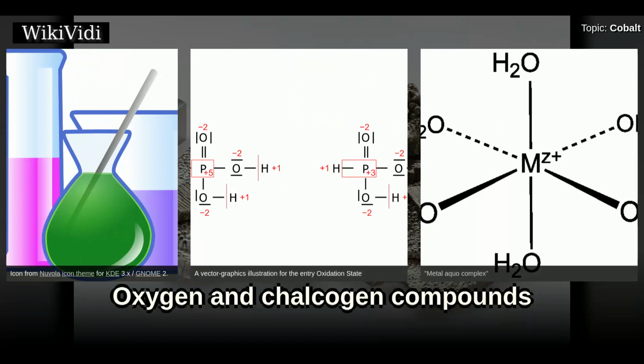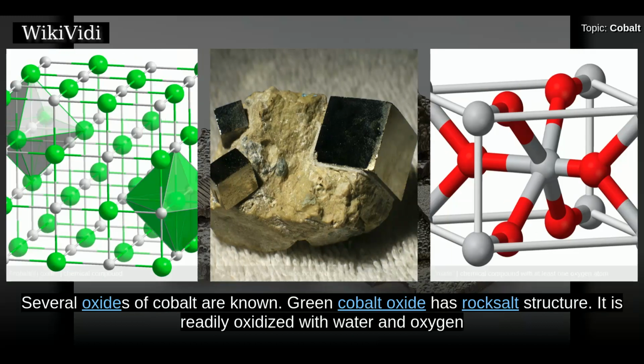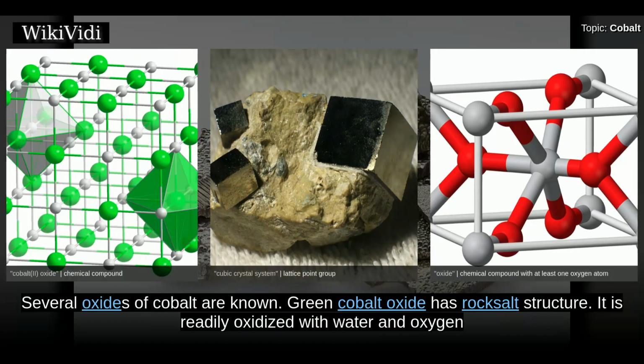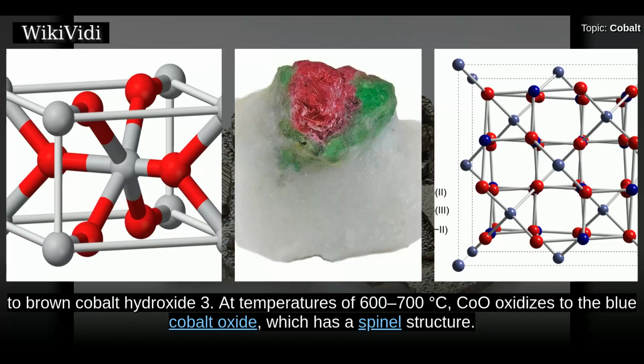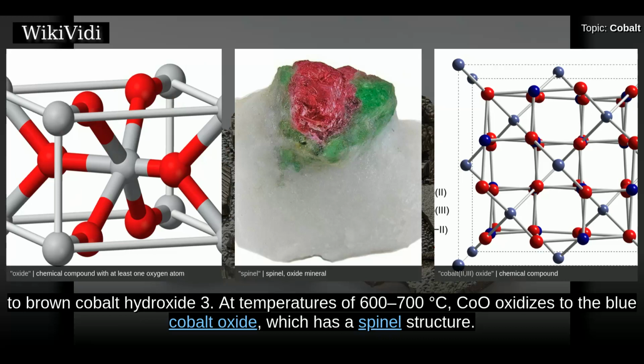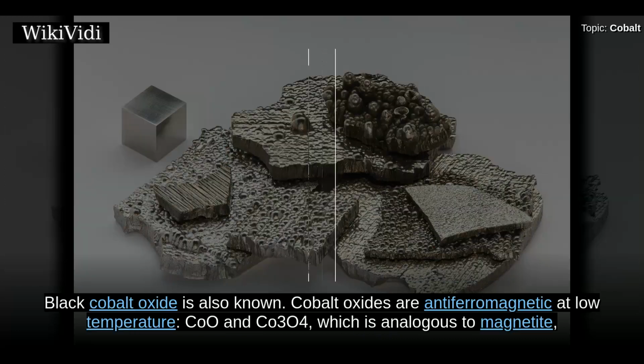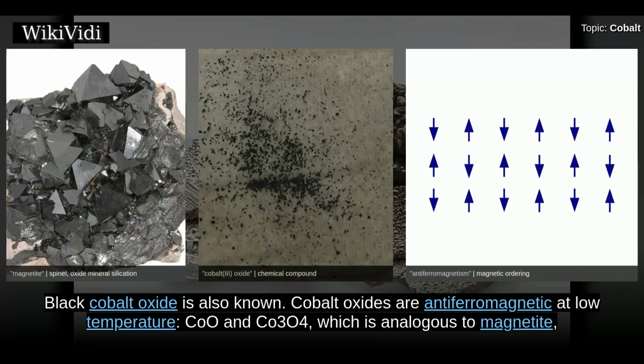Oxygen and chalcogen compounds. Several oxides of cobalt are known. Green cobalt(II) oxide, CoO, has rock salt structure. It is readily oxidized with water and oxygen to brown cobalt(III) hydroxide, Co(OH)3. At temperatures of 600–700 degrees Celsius, CoO oxidizes to the blue cobalt(II,III) oxide, Co3O4, which has a spinel structure. Black cobalt(III) oxide is also known.